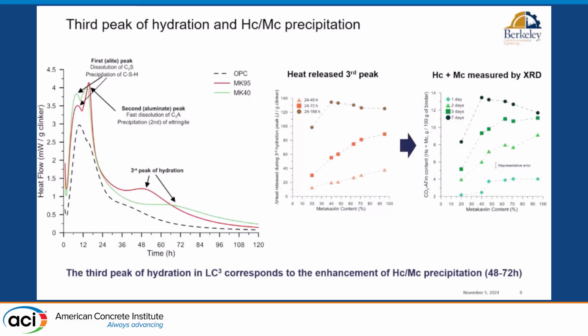So first of all, this doesn't happen in the first 24 hours. So whoever is thinking that what we need to do in order to improve the early age strength or the 24-hour strength of LC3 is to increase the reactivity of calcined clay, you're looking in the wrong place because the reactivity of the calcined clay is coming after that. Before that is the clinker. It's happening after 1 day, between 2 and 3 days actually, and the position of the peak changes as a function of the metakaolin content that we have in the system.